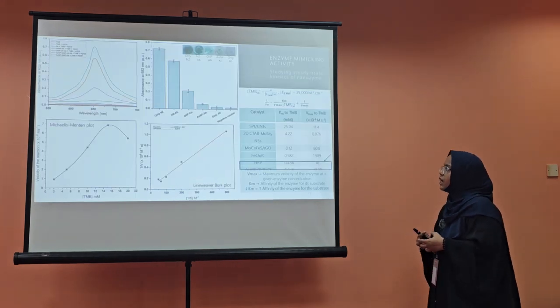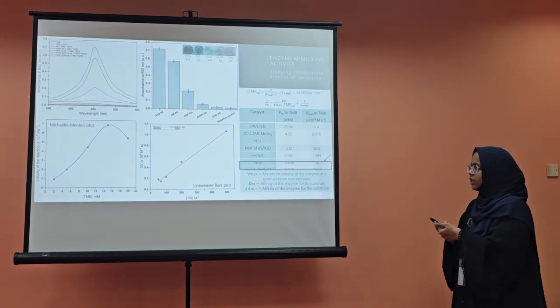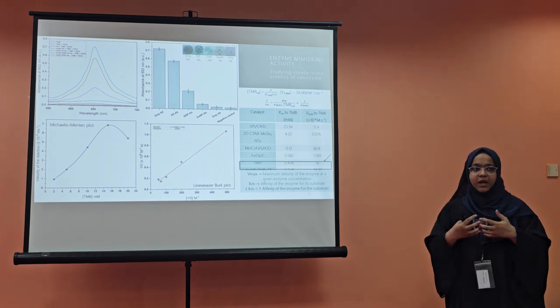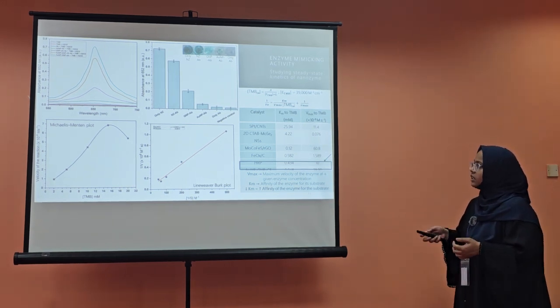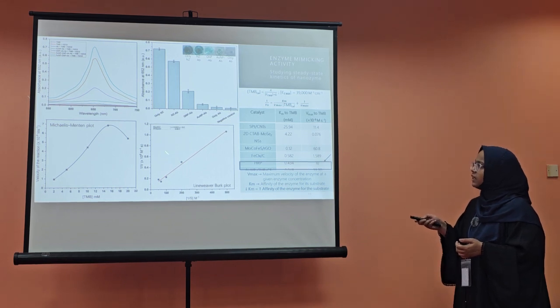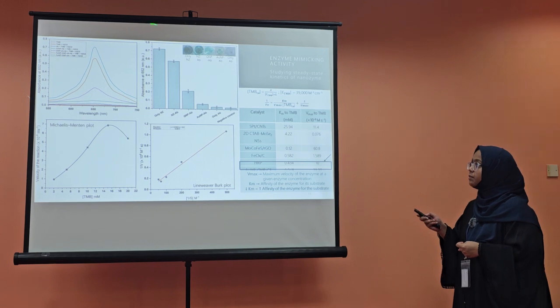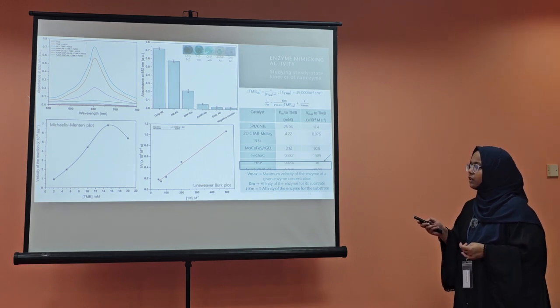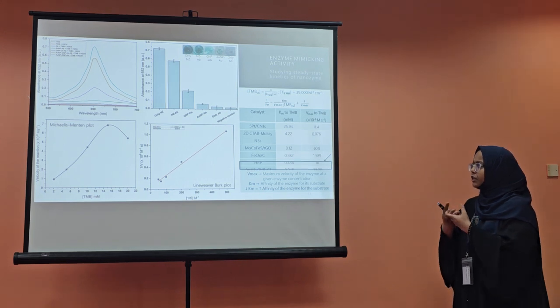For understanding the enzyme-mimicking activity, the absorbance at 652 nanometers was studied, because that is where the maximum absorbance of the oxidized TMB product occurs. As you can see, when only nanozyme was present in the solution without conjugating to the antibody, maximum peroxidase-mimicking activity was observed.